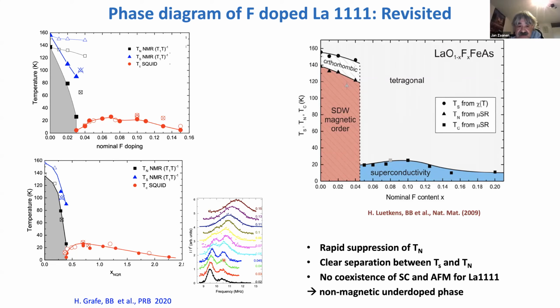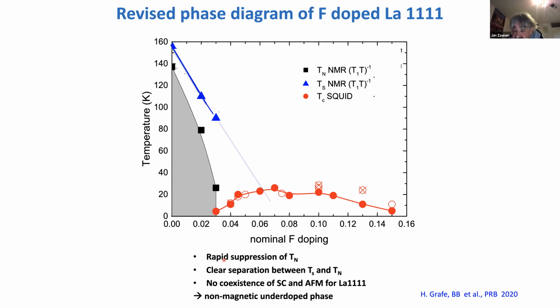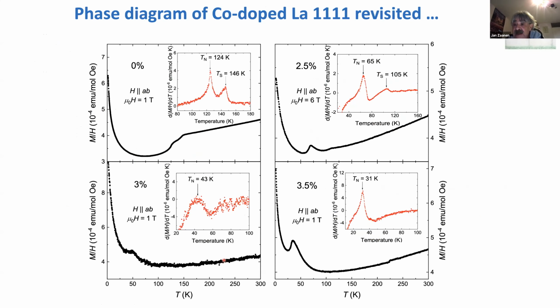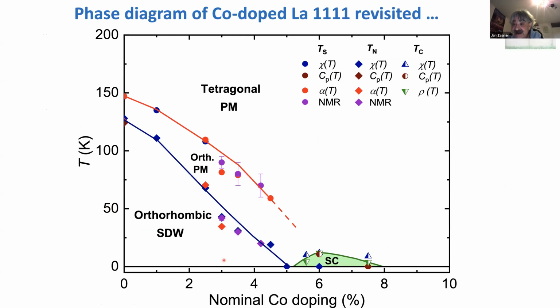I should keep my mouth shut, but that's basically what I'm saying, right? That the lattice may be much more sensitive to the disorder than the electron system is. And that's what we see here. Maybe you lose the structural phase transition, but if you measure the susceptibility, you can still follow the electronic response, which just hits this line.